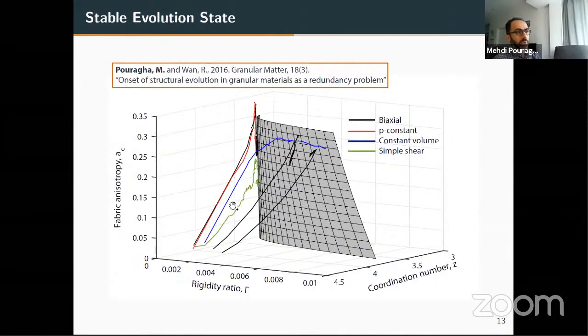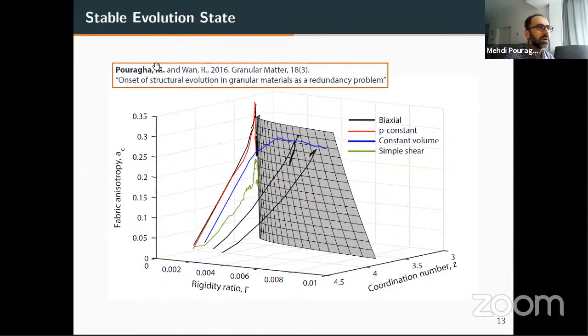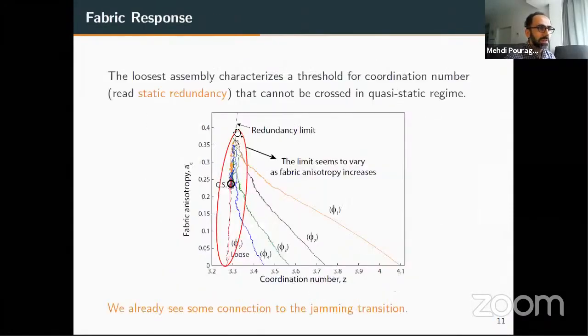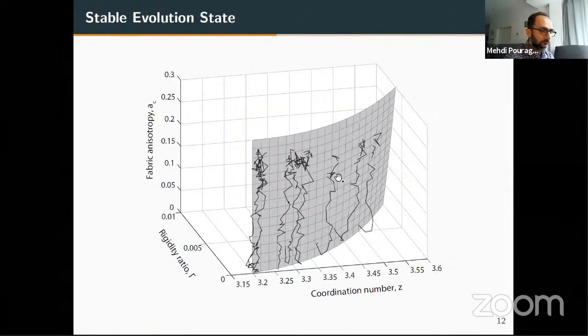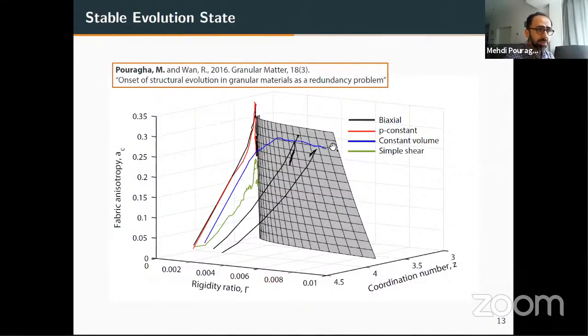Now, what we did next was to compare a bunch of different simulations with different loading controls, with different initial conditions. And the interesting thing was that all those samples, their micromechanical state would evolve toward this manifold, reach that, and they would all stay on it. It seems to be a very good micromechanical attractor, and we call it the stable evolution state, or SES for short. And I'll talk about why this name is chosen in a minute. So this seems to be a very good attractor. And keep in mind that the critical state is also on that. It's a point on this surface, and it seems to have some relation to jamming transition, but we are not clear about it yet.